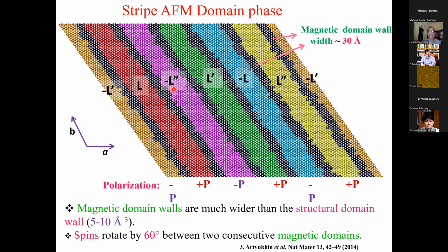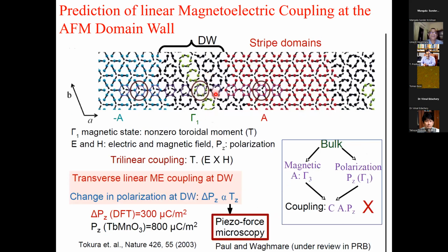And that's what these L primes are: different ordered states of the magnetic spins of the manganese atom. And this being ferroelectric, it also has the electric dipole polarization, which flips from one domain to another. So you have both structural domain and antiferromagnetic domain when you go across this domain wall. Well, what is more fascinating is these domain walls involve a magnetic spin structure which is totally different from what is present in the bulk. So this is the bulk magnetic ordering on the two sides. And at the domain wall, you will see you have a vortex-like magnetic spin ordering. Yeah, and that is very interesting.